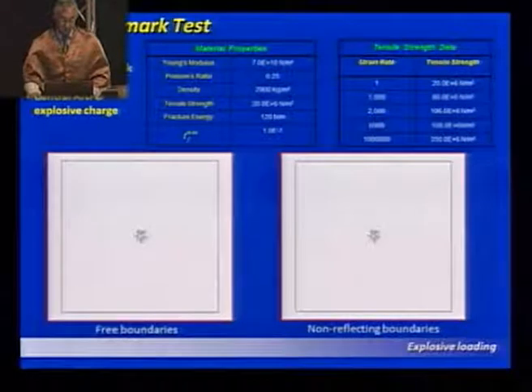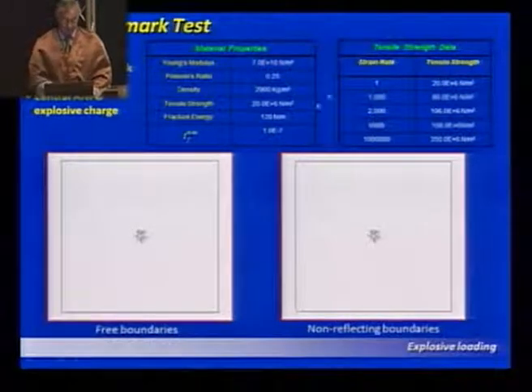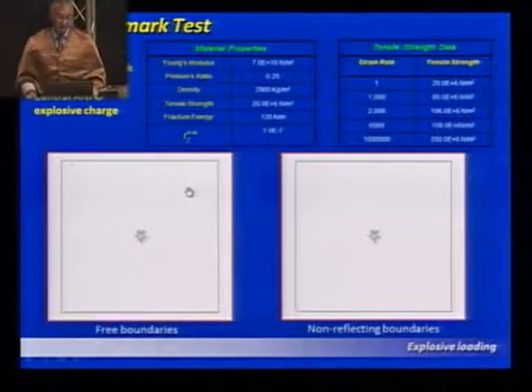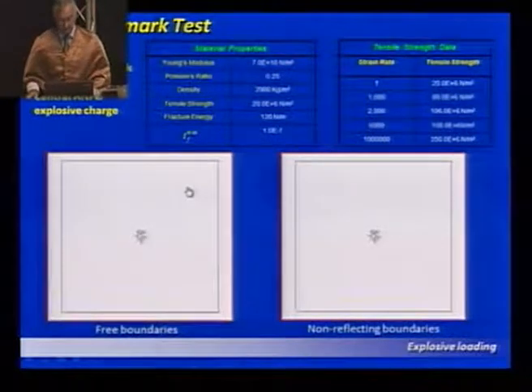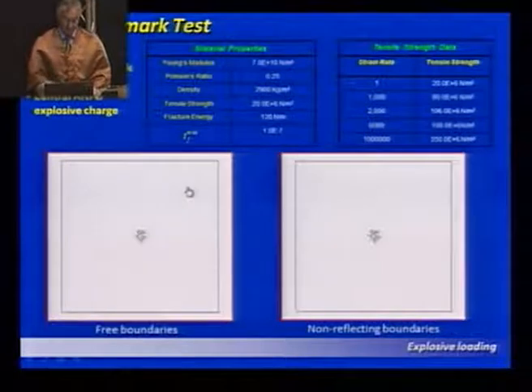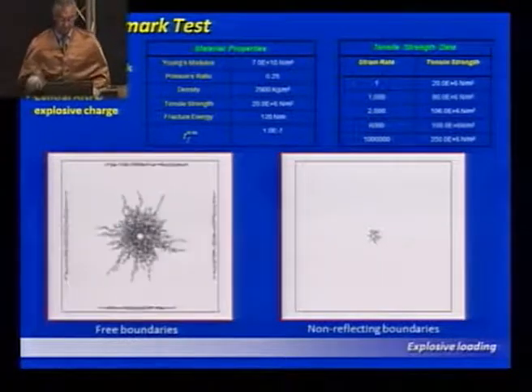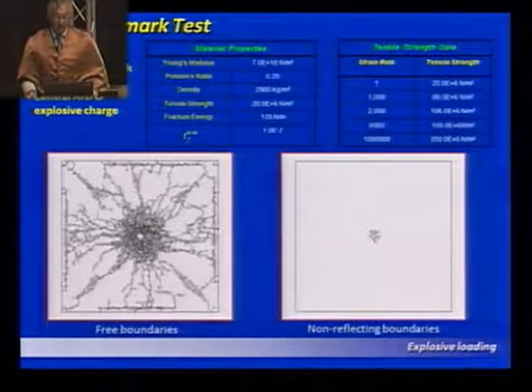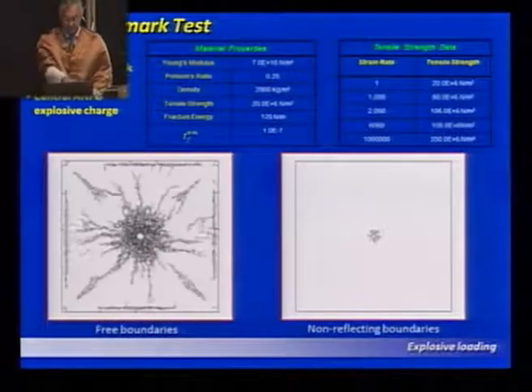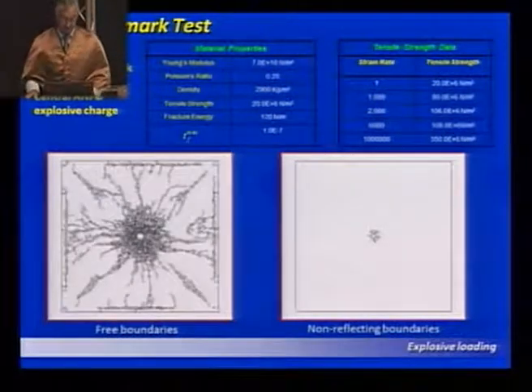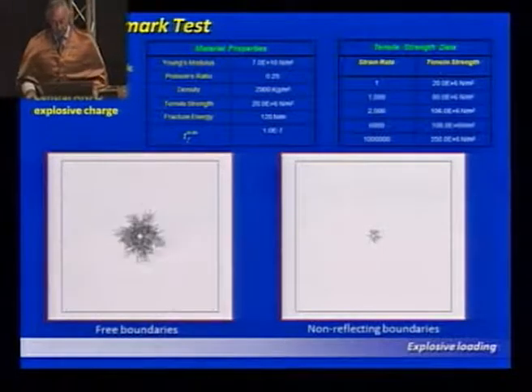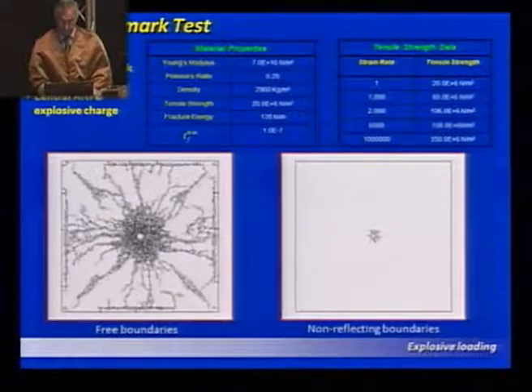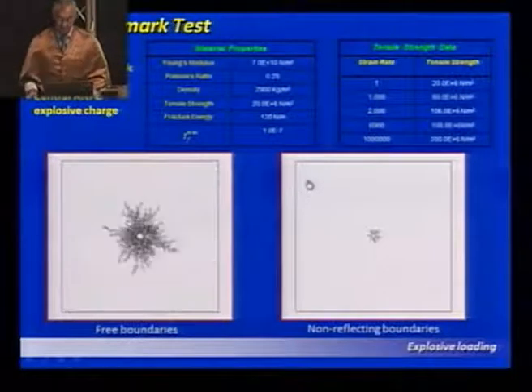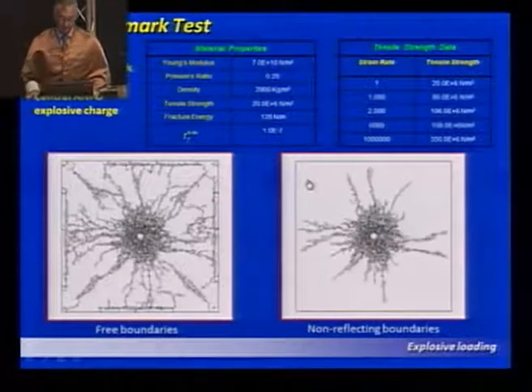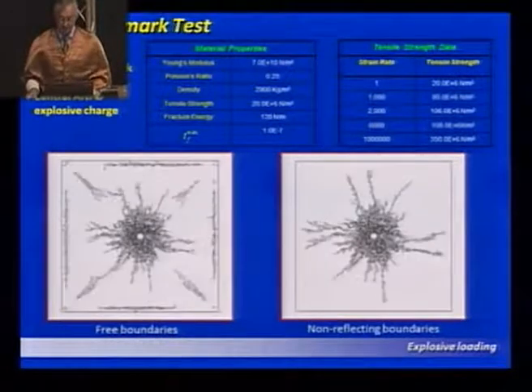And these are two solutions here. This is a case of what is called the HPE benchmark, high performance explosive benchmark test. And what we have here, we'll detonate explosive in that central hole. And then what we find is if the boundaries are free, we get a compression wave, which is reflected back as a tensile wave, causing tensile cracks around the boundary. On the other hand, if you have a non-reflecting boundary, and you allow the wave to pass through, then you simply get the fractures going out and nothing getting reflected at the boundary.